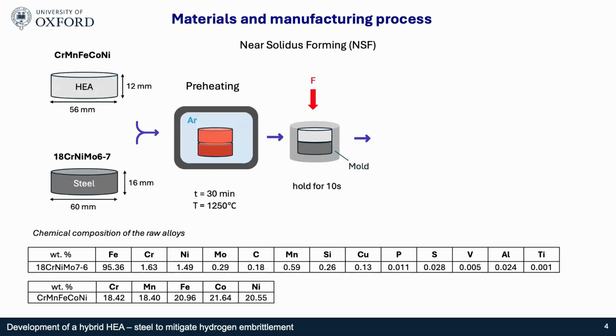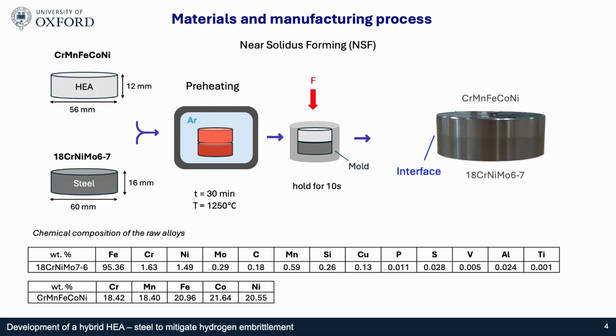So this hybrid material was fabricated through a near solidus forming technique. We have the raw materials, the equiatomic high entropy alloy and a chromium nickel molybdenum steel in a quenched condition, with the chemical composition shown in these tables. Then we preheat these two materials, reaching a temperature close to the solidus point. And then we apply a load in order to join the two materials in this near solidus state and obtain this hybrid material, with the high entropy alloy on top and the steel below.